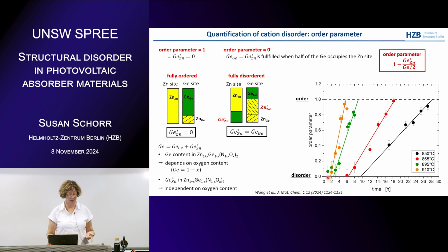So each point is one sample. This is the reaction time, and the different colors are the reaction temperatures. And now we see that our points are nicely ordered if we look for the order parameter, which goes from 1, which is fully ordered, to 0, which is fully disordered. And now you can see that we can tune the disorder by choosing a certain couple of reaction temperature and reaction time. And this is in principle what we want to know, if this is possible.